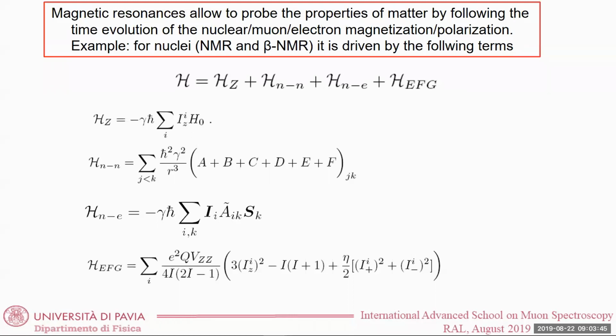Now, the muons are basically, in the MUSR experiment, sensitive to the first three Hamiltonians, except the last one, because the muon is a spin-1/2 particle, so it doesn't have an electric quadrupole moment. So if we apply a magnetic field in MUSR, we'll have this Zeeman splitting. There is a dipolar interaction between the muon magnetic moment and, in general, the nuclear magnetic moments which are present in your system. And the more interesting part in general to study the properties of a certain material is this hyperfine Hamiltonian. At the end of this talk, I will show you that with MUSR, you can even probe this part.